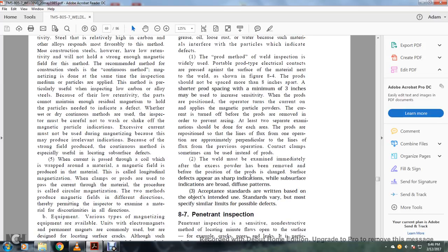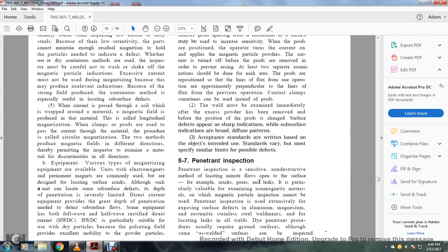2. The weld must be examined immediately after excess powder has been removed and before the position of the prods is changed. Surface defects appear as sharp indications, while subsurface indications show broad, diffuse patterns. 3. Acceptance standards are written based on the object's intended use, but the standards vary and must specify similar limits.